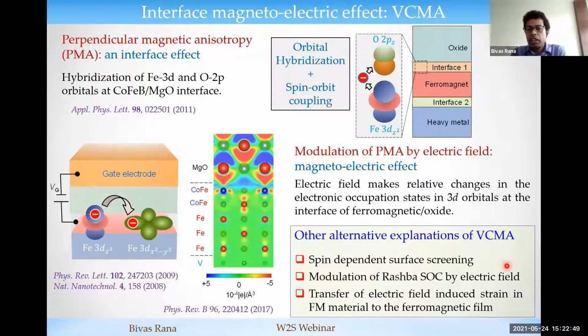And the second explanation is the modulation of Rashba spin orbit coupling by electric field. Basically, theoreticians say that there is a Rashba spin orbit coupling which exists at the interface of the ferromagnet and oxide layer. When we apply the electric field at the interface, that tunes the Rashba spin orbit coupling, and that's how you can tune the perpendicular anisotropy of the system. Another alternative explanation could be, when you apply the electric field through this dielectric layer, it induces some kind of strain in this dielectric layer, and that strain is transferred to the ferromagnet, and through the magnetostriction, the anisotropy of the ferromagnet is changed.